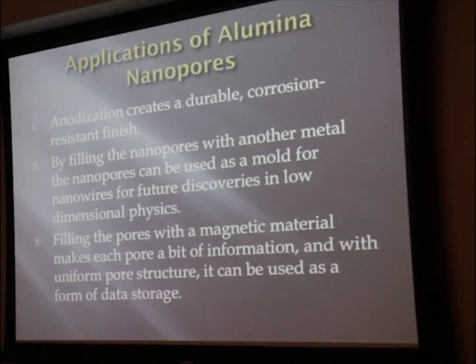So now we have some very nicely ordered pores, and we can see them under the SEM. So what's the point of doing this? Well, first off, anodization makes a very durable and corrosion-resistant finish. So that surface we have there is long-lasting. We don't have to worry about any aluminum wearing over time because we already made that oxide layer.